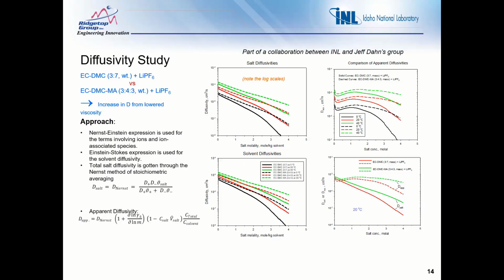The apparent diffusivity is obtained by starting with the Nernst and applying a thermodynamic factor to that. This factor has been developed and published before by John Newman, so this is a well-known way to condition the diffusivity for the thermodynamic effects in solution for batteries. Then these plots on the left, the two in the middle, are the different species type diffusivities given for the salt. These are the Nernst average values given for 3 different electrolytes, in black, red, and green, representing different temperatures for the EC-DMC system: 0, 20, and 40 degrees. And on the right-hand side, we have the apparent diffusivities calculated for the same systems.